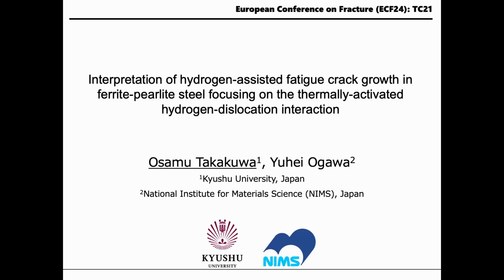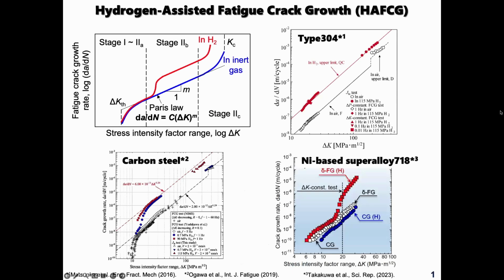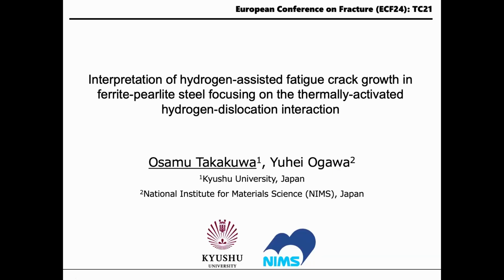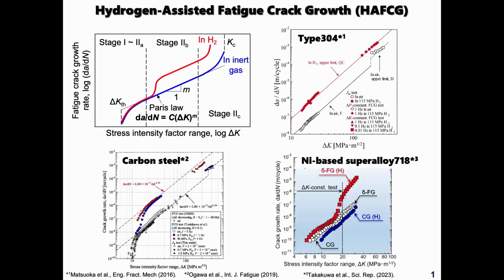Today I'd like to talk about our research framework of hydrogen-assisted fatigue crack growth in gaseous hydrogen environment from the viewpoint of the thermally activated hydrogen-dislocation interaction. The dramatic acceleration of fatigue crack growth manifests in various metallic materials as shown here, but it is still under debate because the phenomenon is so complicated, strongly dependent on the environmental, mechanical, and metallurgical conditions. But one thing I can say for sure is that the presence of hydrogen drastically changes the collective plasticity during the fatigue process, which triggers the severe acceleration of macroscopic fatigue crack growth in various metallic materials.